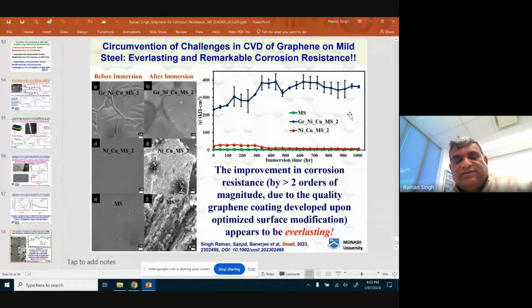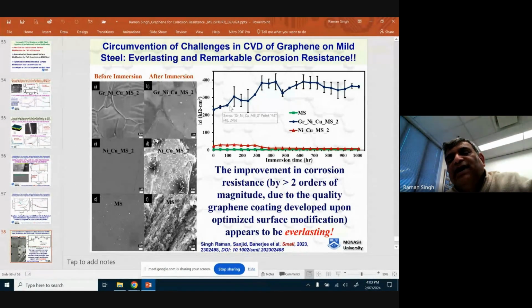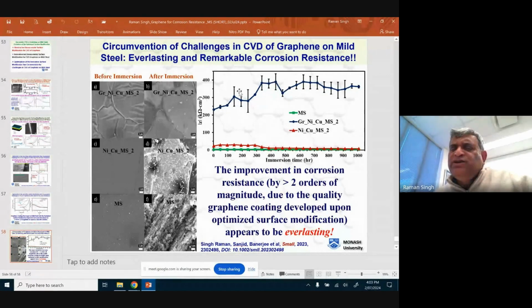That corrosion resistance, I'm showing this plot many times, lasted for over 1,000 hours. If you had just a copper-nickel layer, you could say that the improvement happened because of just the nickel layer. Nickel also gives corrosion resistance. If you had just the copper and nickel layer without graphene, it corrodes, and corrosion resistance is not as good. But if you have graphene on top of that, it gives very good corrosion resistance, more than 2 orders of magnitude improvement, and statistically proven data. It gives perhaps everlasting corrosion resistance. There's no reason why this corrosion resistance should not be everlasting.